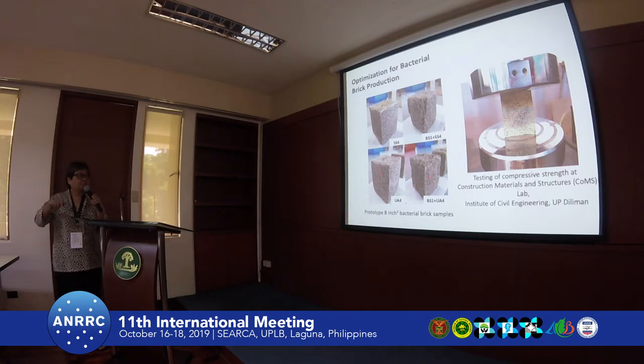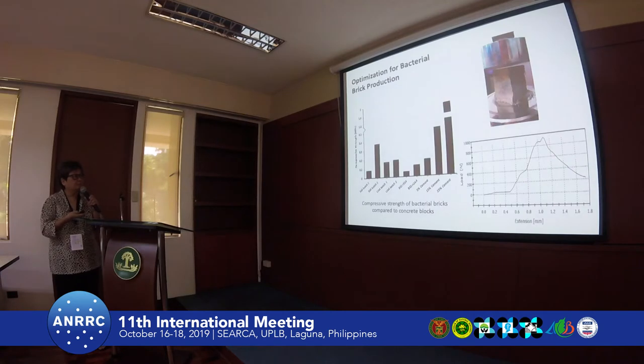Okay? And then after we produced the bricks, we tested for compressive strength, and we found that SS4 alone, when we made the brick, was comparable a little to 15% cement, because this is the compressive strength of 5% cement, 15%, and 25% cement. Now, in construction, you use 25% cement. For our experiments, we were able to get near 15%, and we know we can still increase the compressive strength of our bricks just by the strategy of how to embed the sand in the crystals.